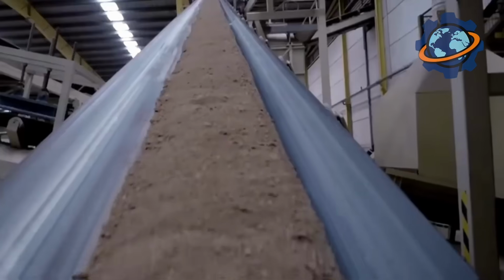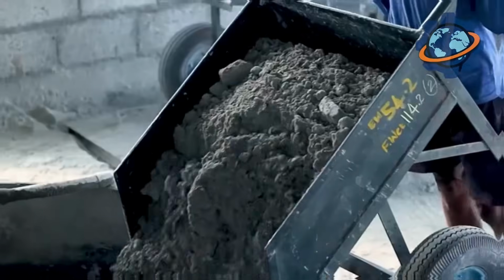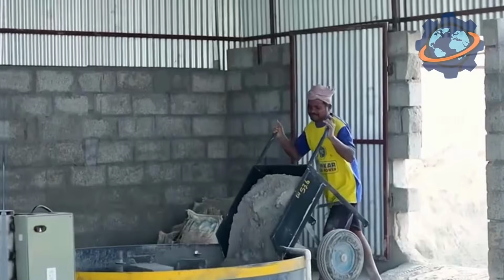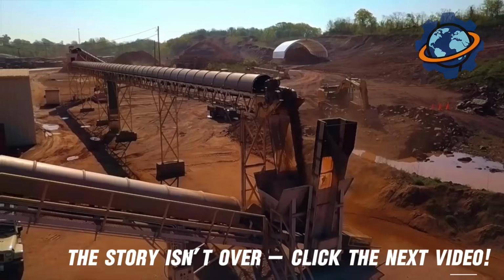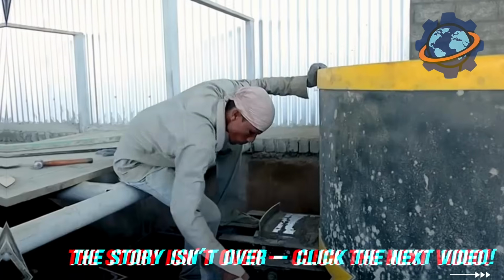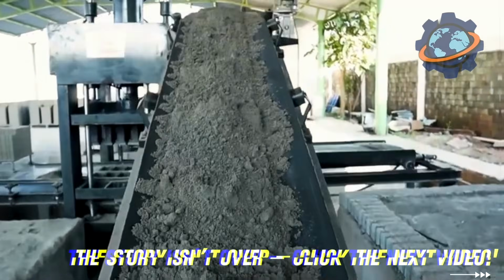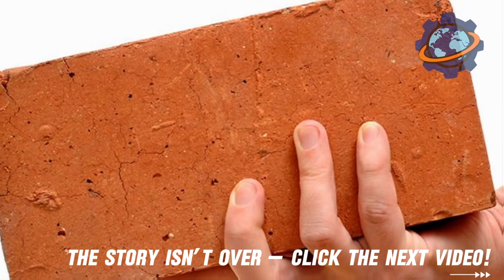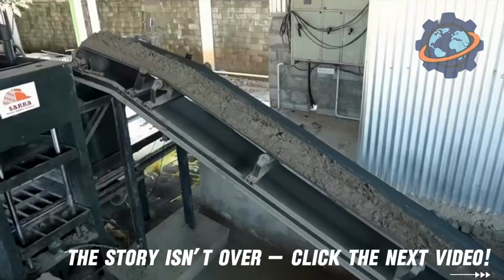Next, the formless mass must acquire its shape. The most common method is semi-dry pressing. The batch, containing a minimal amount of moisture, is loaded into high-strength metal molds. Then, a press exerts an enormous force, measured in hundreds of tons, pressing the mass into a steel die. Thanks to this colossal pressure, the particles get as close as possible, displacing air, and at the output, we get a dense, smooth block with perfect geometry. A green brick. Although it already has its shape, it is still very fragile and not resistant to moisture.